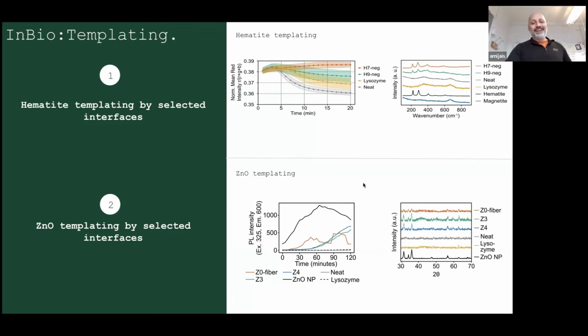And then with zinc oxide, we have an easy life because it has photoluminescence. It can produce a fluorescent signal. So the nice thing is that you create supersaturating conditions. You add the protein, if they have an effect, then you can read it, the fluorescence or the photoluminescence wavelengths. So here in black, you see the nanoparticles, which are the ideal template, and then the proteins are making an effect. At the bottom here, you see lysozyme and this buffer just doing nothing. We confirmed this with XRD this time to see that we have the right fingerprint for this material.